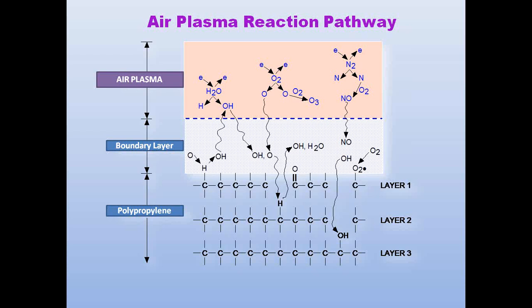The depth of the treatment, we typically get asked this question, is typically around 8 to 10 angstroms in depth relative to the surface. Again, it does not need extremely deep implantation into the material to affect adhesion because, again, the objective here is surface adhesion. And so that is readily accomplished by this pathway.